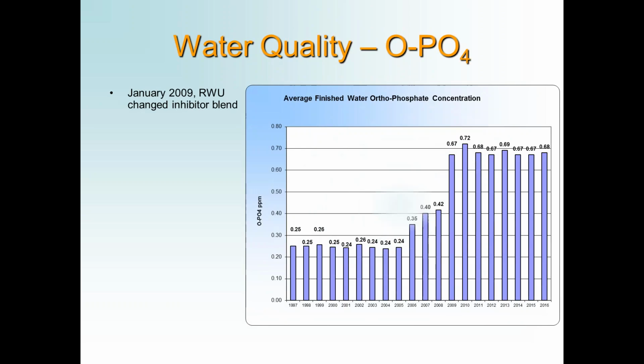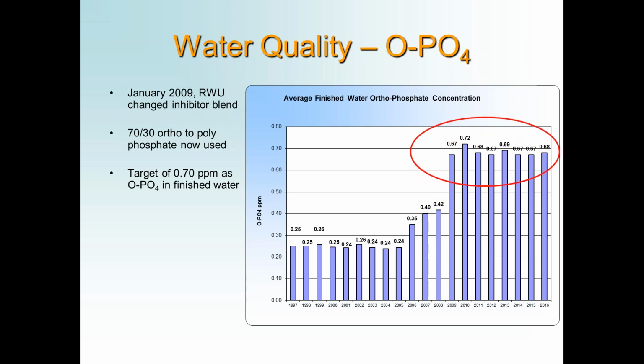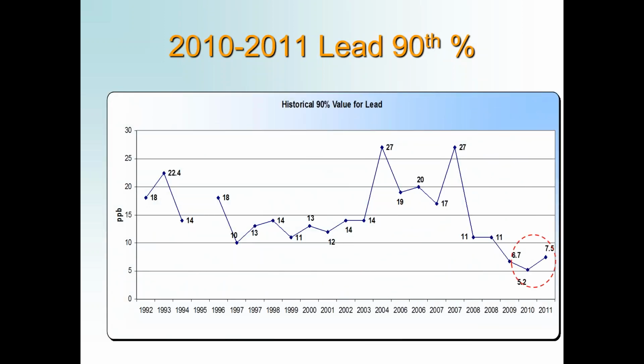What happened in 2009 is that after our studies were completed, submitted to the Wisconsin Department of Natural Resources and accepted, we switched over to a blend of 8600, as Jaron was explaining, their mid-level product, 70% ortho, 30% poly. Looking at the numbers from previous years, going back in the 90s, we were carrying an average ortho level of about 0.25 parts per million. In 2006, when we changed to the 40-60 blend, our orthophosphate went up to about 0.4 parts per million. Then with the switchover in 2009, we're looking at a target level of 0.7 ppm, and that's basically where we hit. So we almost tripled the orthophosphate level that we're carrying in our finished water out in the distribution system, which accounts for a lot of the improvement.